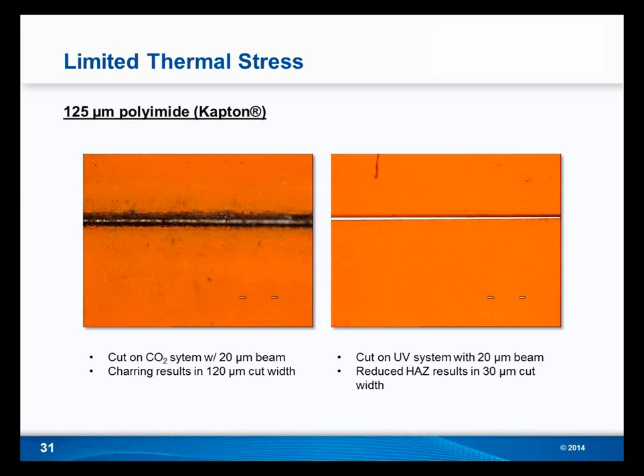So in this case, what we see is a 125 micron thick polyimide. The one on the right was cut with a UV laser, and the one on the left was cut with a CO2 laser. And you can see the difference in the thermal effect on the material. On the right, it's minimal. And the reason for that is not only are we using small power to start with, we're also able to control our parameters really tight, depending on which material we're processing. So even if we have a laser with 6 watts or 10 watts of power, we may only be using 3 watts to depanel 125 micron thick polyimide. So that's the great part, that flexibility, where you can go from flex to rigid with the same machine.